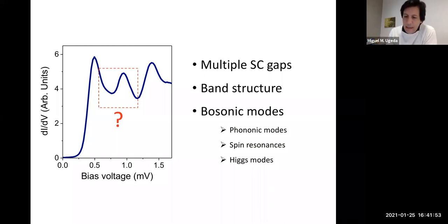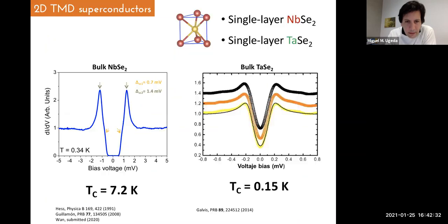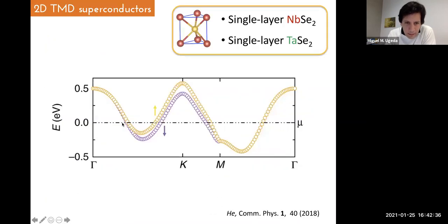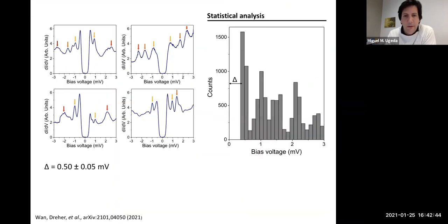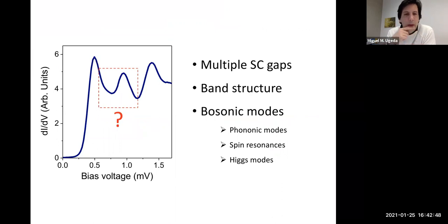So one possibility would be that they could be coherence peaks because we have multiple gaps, but that's not realistic because then we would have four gaps, and that's not realistic in a superconductor. So I guess we can rule it out. It could be a feature of the band structure, but if you look at the scale that we have, it's 1.5 millielectron volts. And you can believe me, I can go back for a second to the band structure. We are talking about an energy window, which is here, and there is nothing that can explain the emergence of so many features within the narrow energy window.